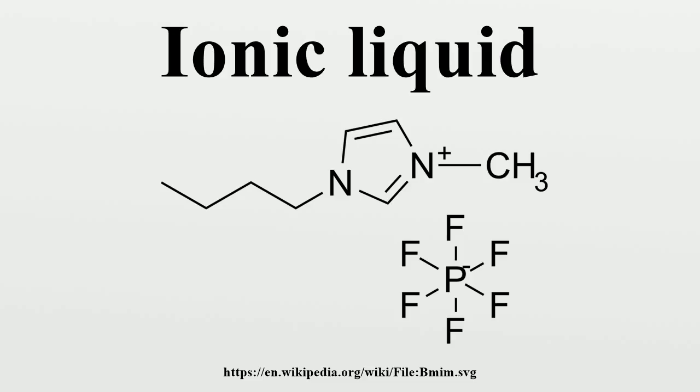The melting point of 1-butyl-3-methylimidazolium hexafluorophosphate, with an imidazole skeleton, is about -80 degrees Celsius, and it is a colorless liquid with high viscosity at room temperature. If a highly asymmetric cation is combined with a highly asymmetric anion, the formed ionic liquid may not freeze down to very low temperatures, and the glass transition temperature was detected below -100 degrees Celsius in the case of ionic liquids with N-methyl-N-alkylpyrrolidinium cations and fluorosulfonyl trifluoromethanesulfonylamide.